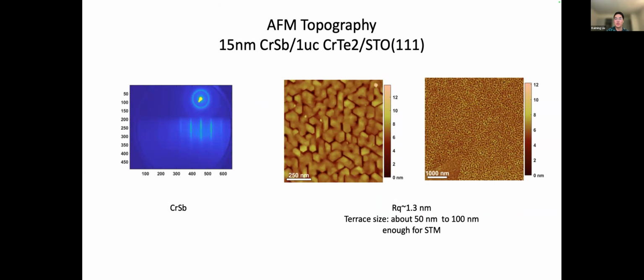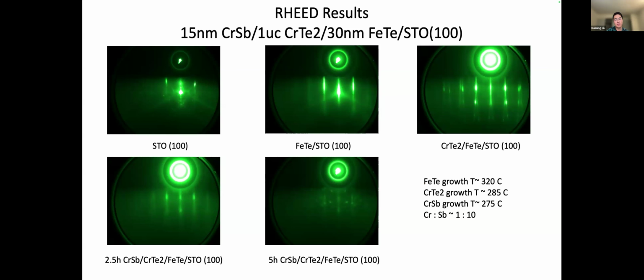The third recipe is to combine the first and the second together. The RHEED pattern for iron telluride is streaky, and the RHEED pattern for chromium ditelluride is streaky and has some forks at the end. So after growing chromium antimony for 2.5 hours and 5 hours, the streaks remain but become dimmer, which indicates possibly a three-dimensional island formation in some regions.